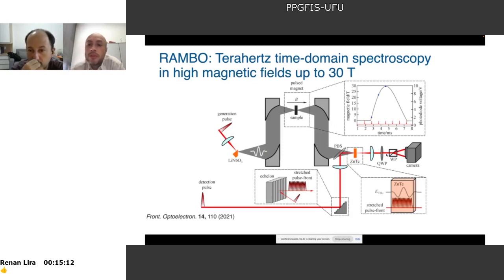This is very difficult to do. The discharge necessary to produce 30 Tesla is very large. You need quite a big capacitor bank to give this discharge. And the problem is that since you can only use one single shot of light, the signal to noise ratio is very low. So you need to repeat, for example, each configuration something like 50 times. Every data point is collected 50 times in order to have a good signal to noise ratio.